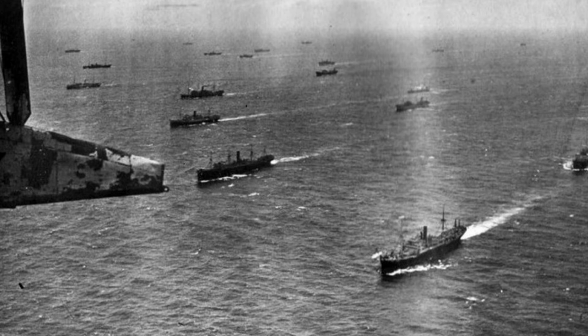The economics were equally conclusive. A Liberty ship cost about $2 million to build. A Victory ship cost $2.6 million, roughly 30% more. But Liberty ships carried a 4.6% chance of catastrophic failure during service. According to 1944 data, disasters that claimed an average of 18 lives and destroyed cargo worth several times the ship's own cost. The Victory's 0 failure rate meant that the extra $600,000 construction cost paid for itself within 6 months, simply through eliminated risk and lower insurance premiums.